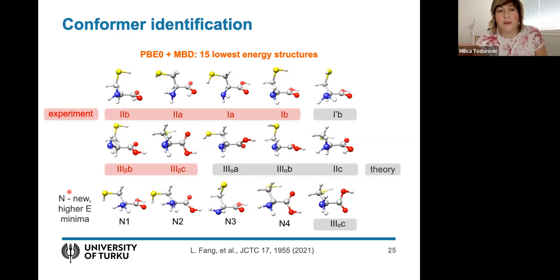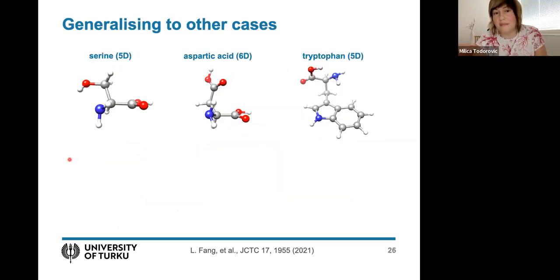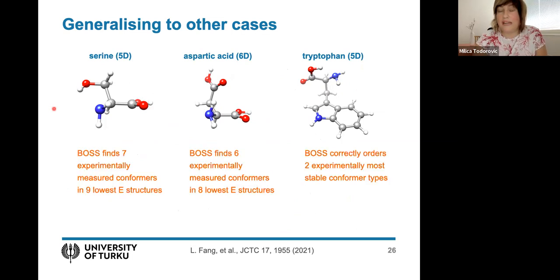So we wanted to know if this is somehow general. So we applied these approaches to other similar molecules. Serine and tryptophan are also 5D, five-dimensional systems, so they have five torsional bonds. And aspartic acid here has six torsional bonds. Again, we performed a single active learning search for all of them until the energy models converged and we extracted all the local minima.